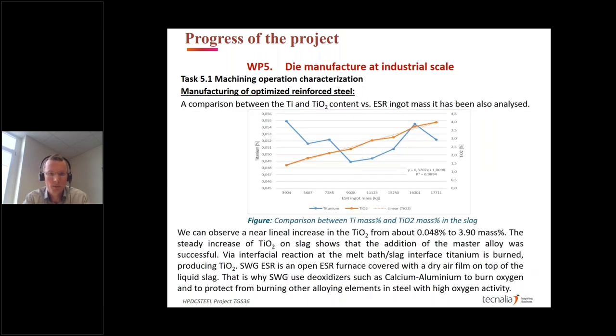recovered during the remelting. And what we can see here is a comparison between the titanium concentration of samples we have taken during the remelting process as a function of the ESR ingot mass. And also what we can see again is the titanium oxide concentration of the slag pool as a function of ESR ingot mass. And there was a very stable recovery rate of the titanium during the remelting process. So these are very good results because it means that our feeding was stable during the whole ESR ingot mass remelting.